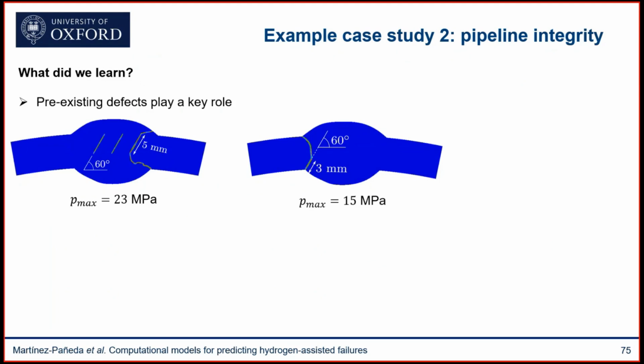So we tried to conduct a systematic study where we try different sizes of defects along different orientations. And what we found is that the most critical scenario, as you would expect, is one where you have defects lying along the heat-affected zone. And we saw that these defects of 3 millimeters could reduce the critical pressure to 15 megapascals.